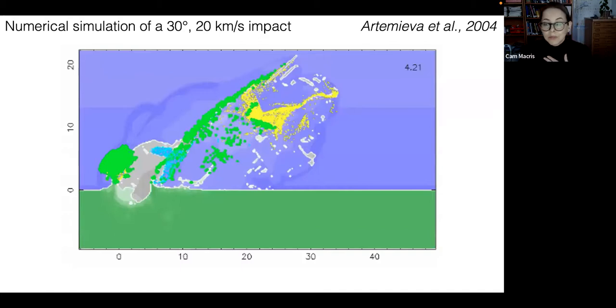So if we look back at this final shot of Artemieva's hydrocode model, our results offer possible temperature-time paths for this yellow molten future tektite material here. We can now envision what might happen to this tektite parent material if the model was run for much longer times. Some of the melt would fall to the ground first, cooling to form those layered or Muong Nong tektites. The rest of it would continue to travel away from the crater, entrained in the hot vapor, which is going to buffer their melt temperatures for longer, until at some later time the plume dissipates and those airborne melt particles cool very quickly and continue along their ballistic pathways to their final location.